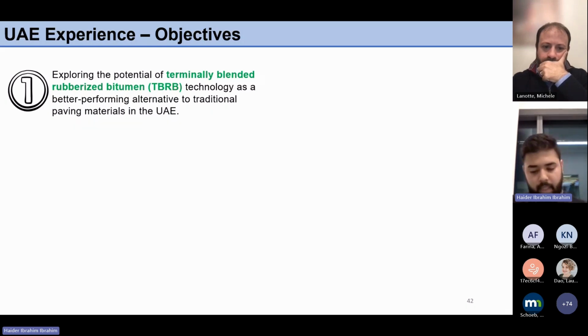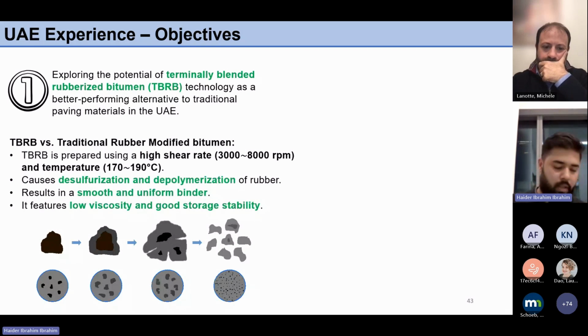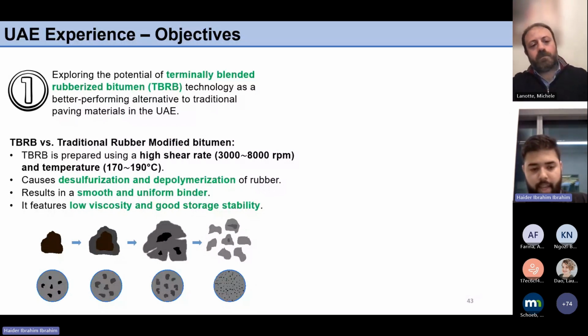So why terminally blended? Why not use the traditional rubber modified bitumen produced through the typical wet process? Well, the reason was that the terminally blended rubberized bitumen, the TBRB from here on, exhibits low viscosity and very good storage stability, owing to the fact that it's produced at a very high shear rate and at elevated temperatures. The figure below shows how this high shear rate and temperature affect the crumb rubber inside the bitumen.